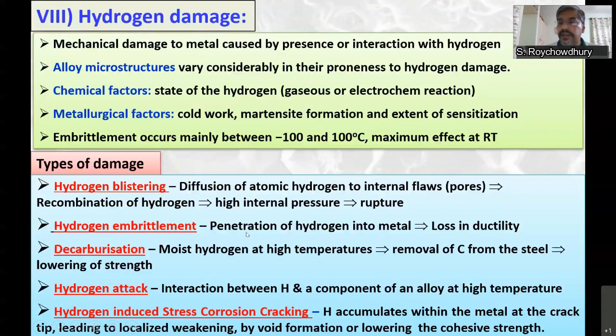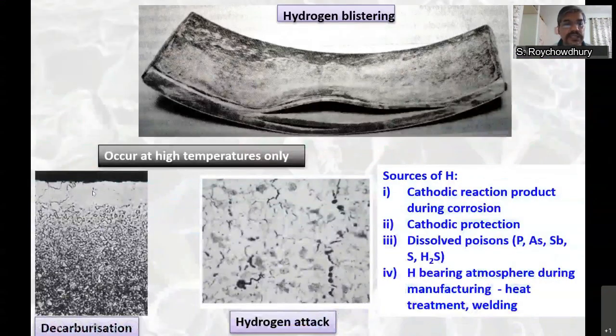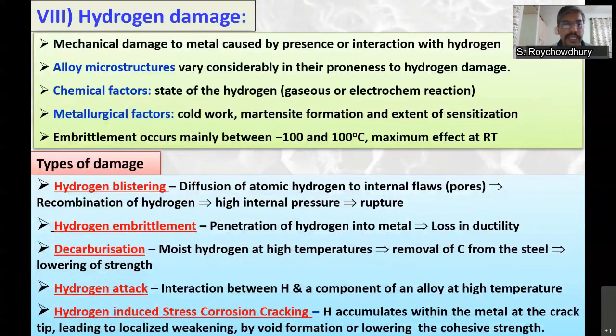Hydrogen embrittlement: if hydrogen is present in the metal, it increases the embrittlement or reduces ductility. Decarburization and hydrogen attack. Hydrogen attack mainly occurs at high temperature, moist environment, in which the hydrogen reacts with one of the alloying elements in the steel. It can react with carbon and remove the carbon from the steel surface. As you can see here, it gets decarburized. The problem is, if you remove carbon, the strength comes down, so the material becomes weak.